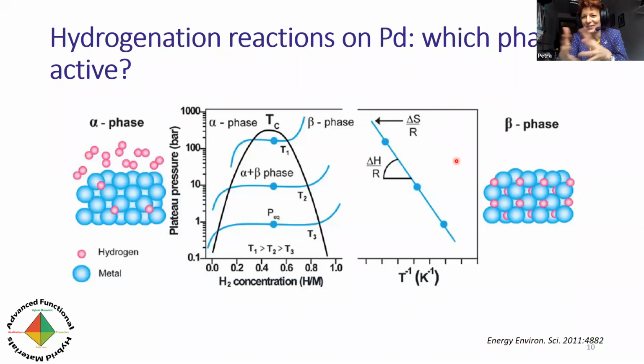One thing is, and I'm sure that Bernard and of course Herman will be quite familiar with this, that when palladium is exposed to hydrogen, it does react with it. So it's not just the reaction that would happen on the surface, which you would expect from platinum, for example, that when it's exposed to hydrogen pressure, then hydrogen molecules would chemisorb on the surface and split into atoms. In the case of palladium, what may happen is that, and what does happen in quite a broad range of conditions, is that the split hydrogen atoms may diffuse inside of the palladium metal into the bulk.